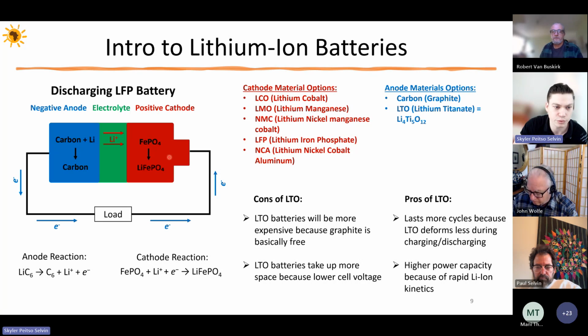And that's for a few reasons, but the major reason is because when the lithium ions come in and out of the carbon material, of the graphite material in the anode, it changes the volume of the material. So the material is constantly expanding and contracting, and this causes physical strain, cracking, and just degradation of the material over long periods of time. But lithium titanate, they call it a zero strain material. As the lithium ions come in and out, it doesn't change volume nearly as much, lending to longer lasting batteries, sometimes in excess of 10,000 cycles.